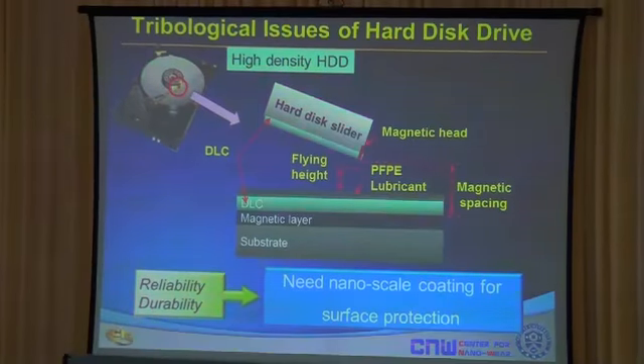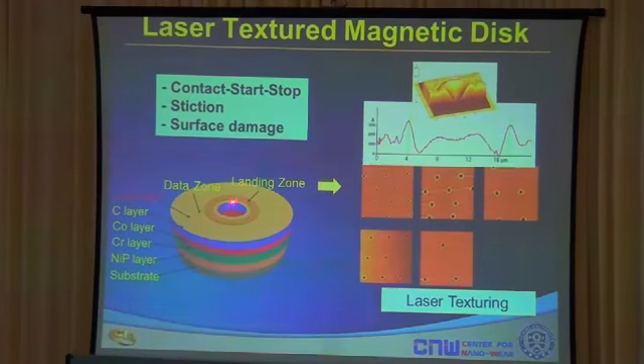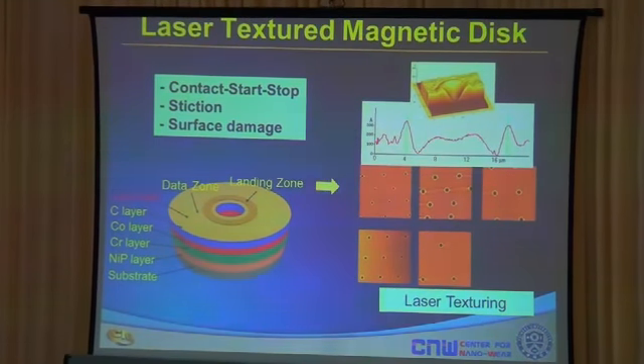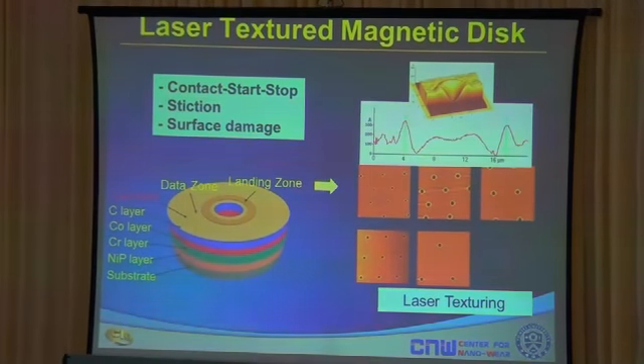Obviously, the problem faced is that because sometimes you may have contact between the slider and the disk, you will have friction and wear problems. And this is what we want to avoid. If we look at the way the disk is structured, it is also composed of complicated textures, including what we call a landing zone. The landing zone is a textured region where you have small protrusions on the surface, and these are made by laser texturing. The purpose of these textures is to reduce the stiction between the slider and the disk when the slider lands on the disk when you turn off the computer. Without these grooves, the slider, because of its smoothness, will stick right on the disk and you will not be able to start the disk. So laser texturing is used to make such grooves, such patterns.